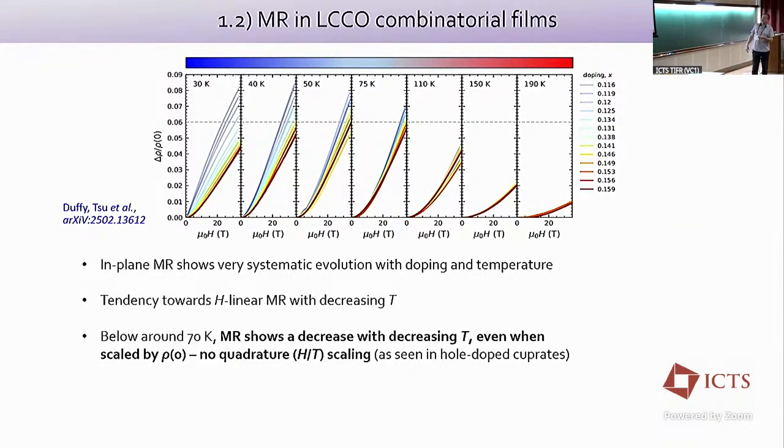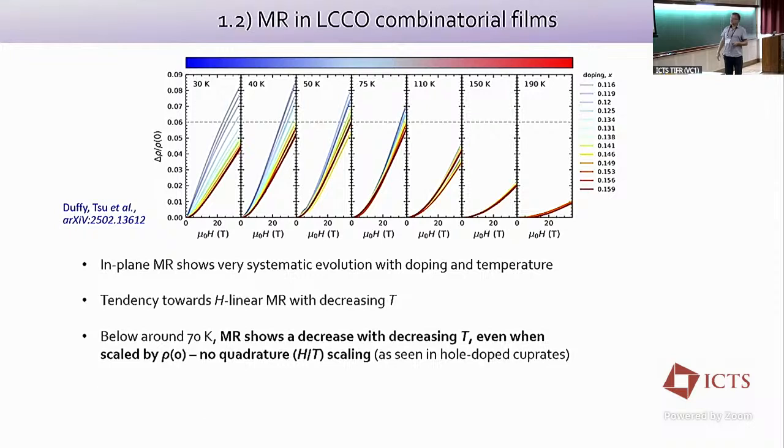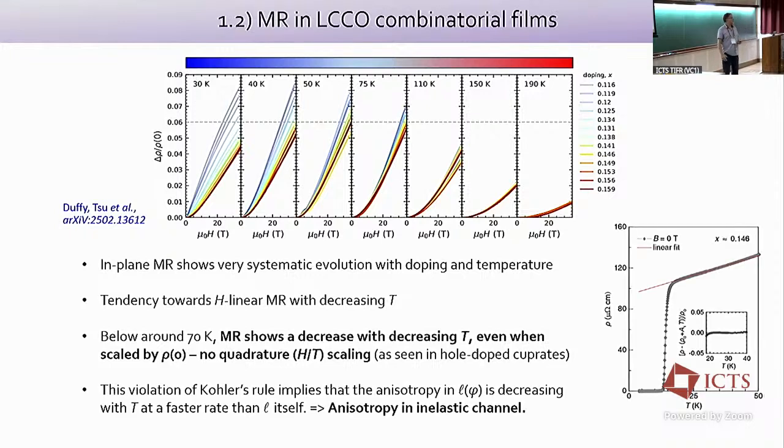Okay, so here I show it going down to low temperatures, around 8 Kelvin. You can see it continues to drop away and get smaller and smaller. I don't show the magnetoresistance in the superconducting state in that plot. It's transverse, yes. The longitudinal is about 5% of the transverse, so there's a small longitudinal component. And it says that this magnetoresistance is orbital in nature. Yes, indeed.